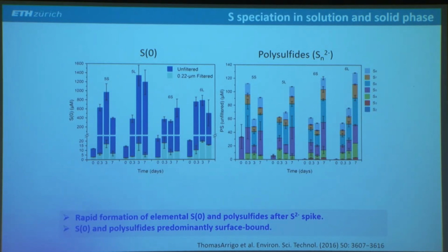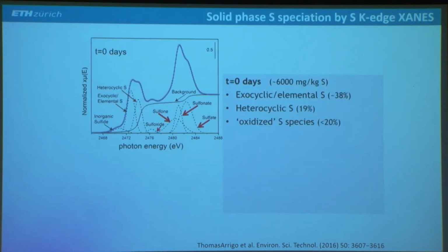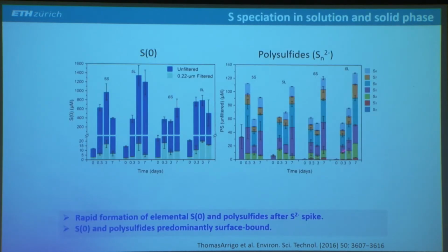On the right side, you see polysulfide formation. And again, sorry, I'm pressing the wrong button here. Again, you see that there's a very rapid formation of polysulfides, mainly S5 and S6 are the biggest fractions. And also these polysulfides turn out to be to a large degree associated with the particle surfaces. So this is simply the result of this reaction that I showed, that part of the sulfide reacts with the iron minerals to form elemental sulfur and polysulfides. This really happens. It shows that the flock iron is very reactive with respect to sulfide. It's not protected by organic matter.